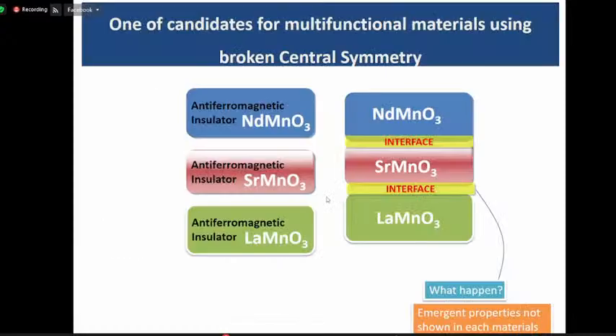Okay, let's see what happened in this superlattice. This superlattice is composed of three different kinds of layers: lanthanum manganese oxide, strontium manganese oxide, and neodymium manganese oxide, and we repeat them again and again to make a superlattice. All layers are antiferromagnetic insulators. But if we put them together, then at the interface, something happened.